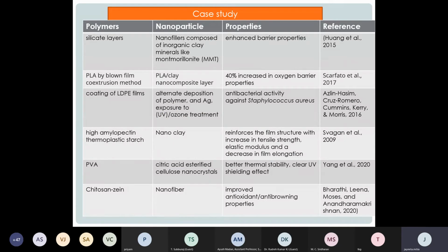A few studies have been done on different polymer and nanoparticle combinations. For example, silicate layers. The nanofillers are composed of inorganic clay minerals like montmorillonite, which has been used to enhance the barrier property, and this study was done in 2015. Polylactic acid by blow film co-extrusion method was used, and clay nanoparticle was incorporated to form the nanocomposite, and they found a 40% increase in oxygen barrier property. Which is significant. A 40% increase means this can be very well used for food material which degrades because of oxygen transfer through the packaging film. Coating of LDPE film.